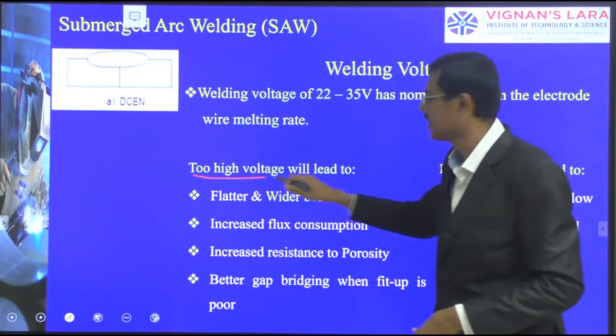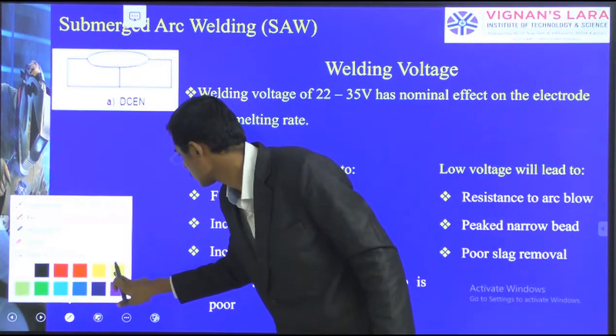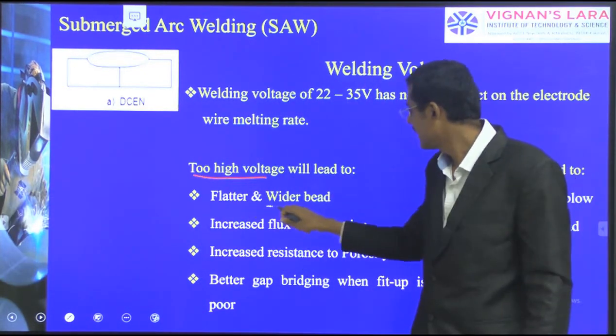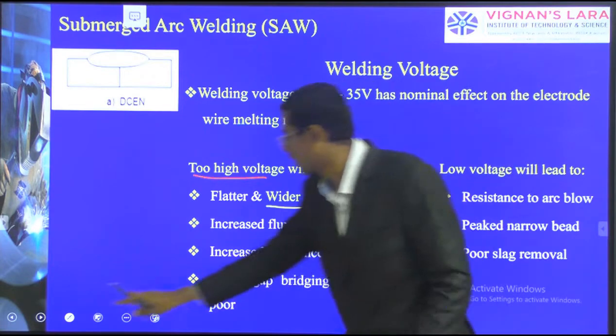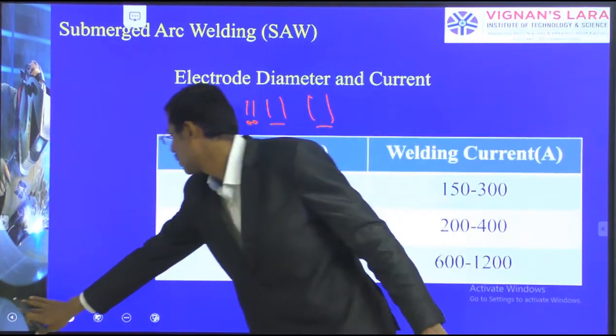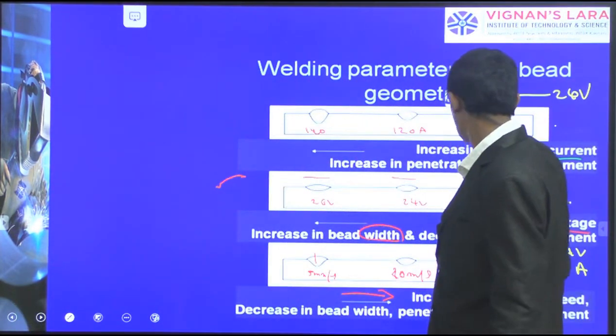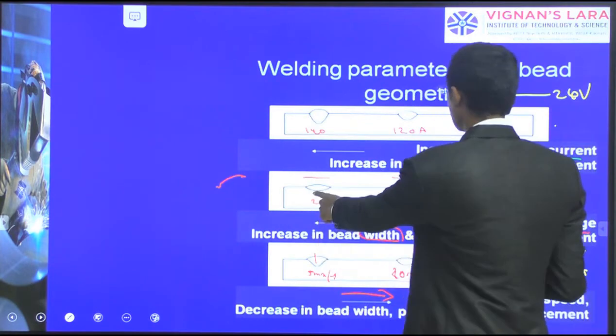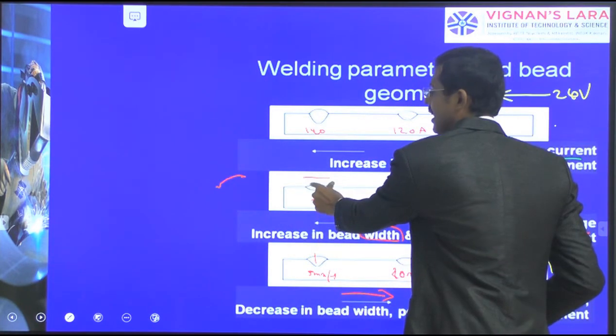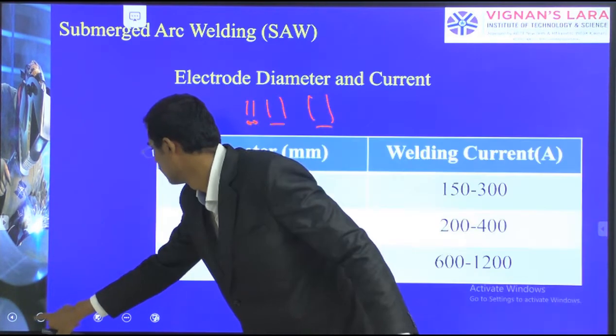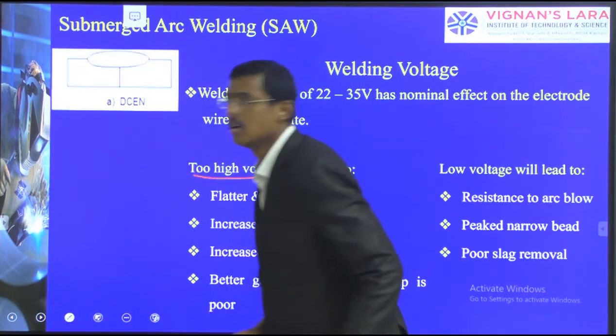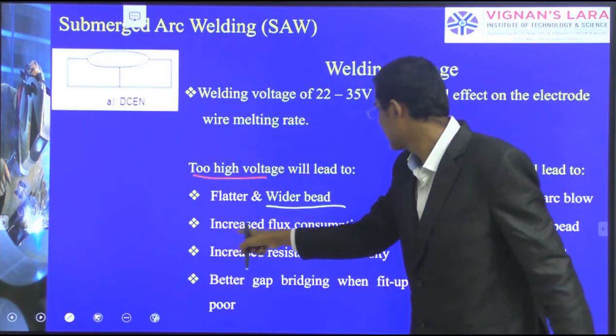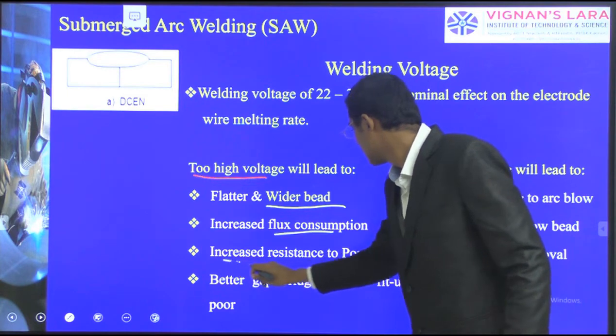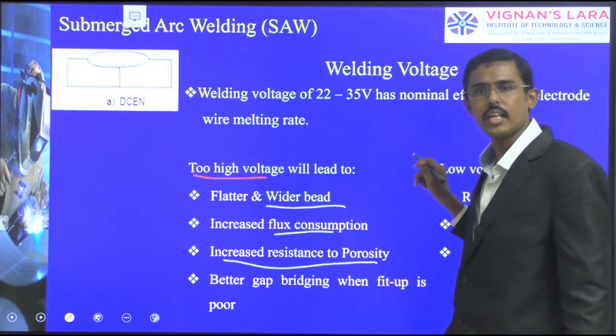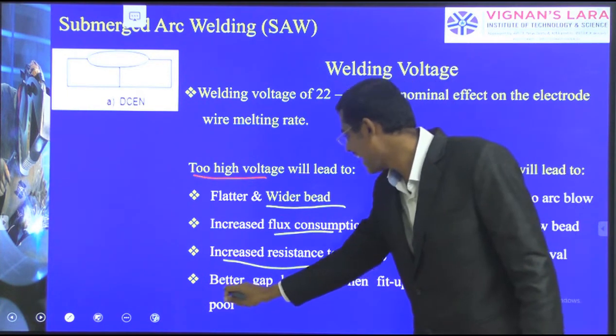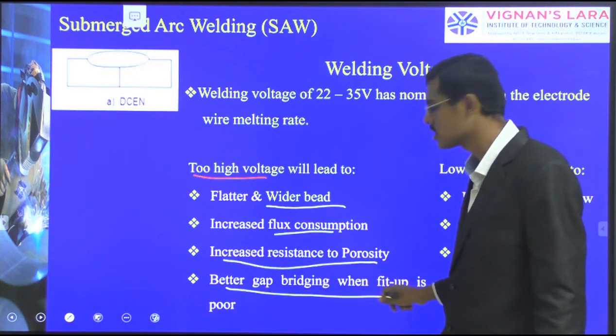If it is too high, what happens? If it is too high, a wider bead occurs. See, increasing the voltage, a wider bead occurs. Now only we have seen wider bead. And with increased flux consumption, increasing resistance to porosity, all will form here. Better gap bridging when the fit-up is very poor.